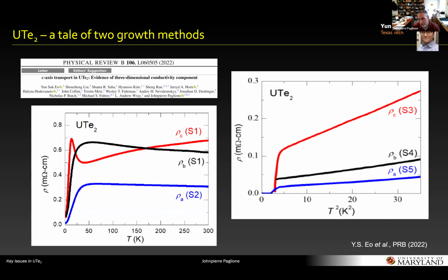And why would that selectively affect the C axis and not the B and the A axis? Well, that's precisely my point: I'm trying to understand the band structure. If it's all the same Fermi surface, I don't quite understand how you would get this selective response without some fine-tuned model. Or some quasi one-dimensional physics, perhaps? That would be interesting, yeah. We certainly have some other interesting data that we don't quite understand that shows some onset of anomalous behavior at this temperature, but I'm not willing to talk about it.